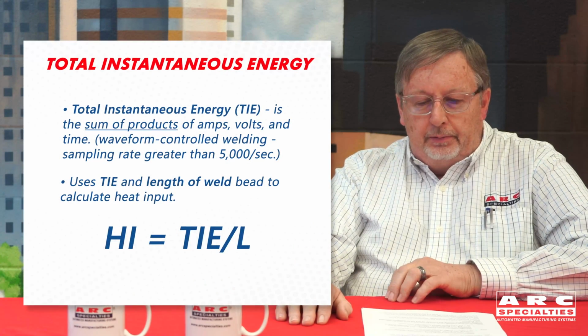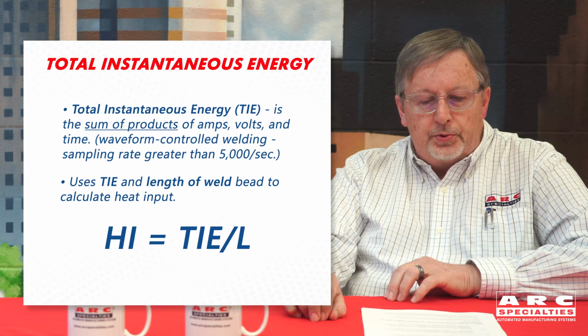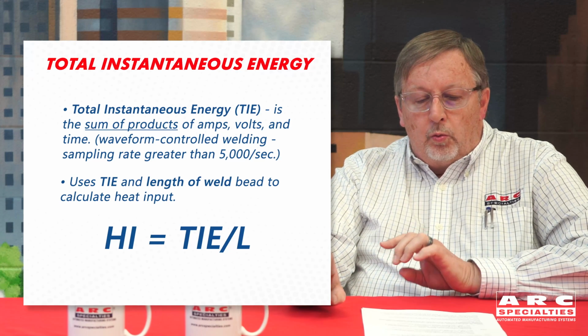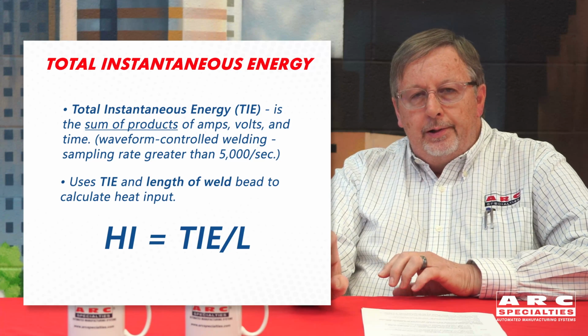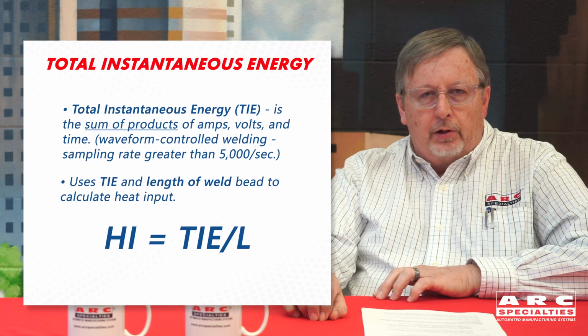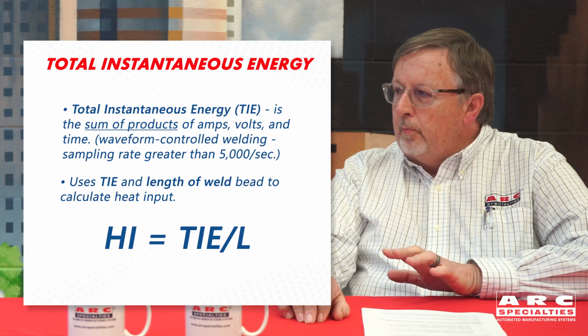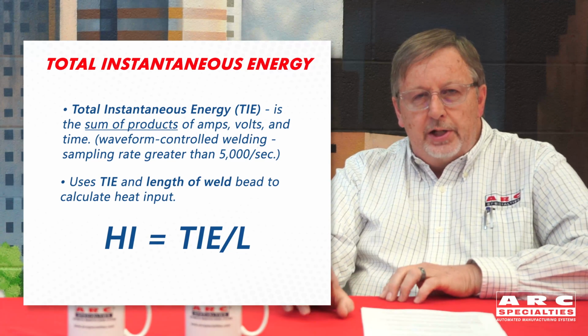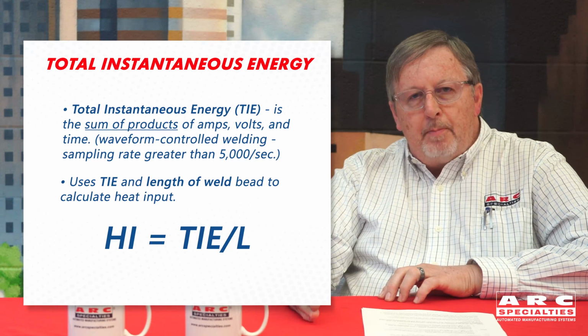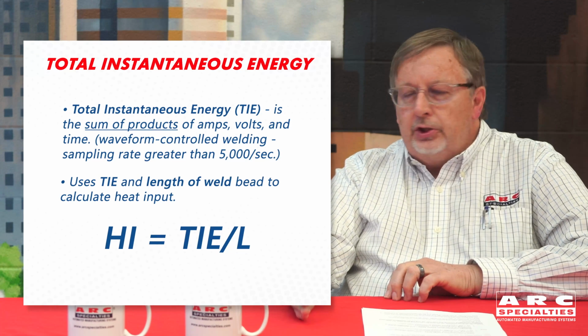Well, one of the committees that I work on is developing a standard called B2.5, and it is a standard that will help everyone understand how we physically measure these quantities, so we can consistently quantify heat input. Now, total instantaneous energy is the sum of the products of amps, volts, and time. And we call it instantaneous because we are sampling that waveform at least 5 kilohertz, or 5,000 times a second. So even though that waveform may change abruptly during each cycle, we're capturing those values and making those multiplication measurements at each of those instants.